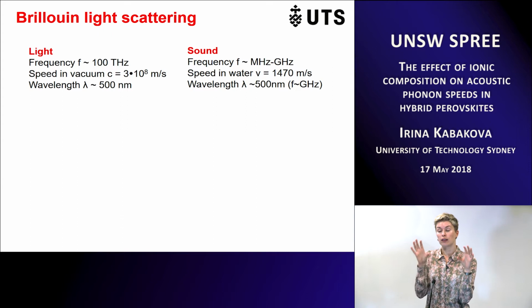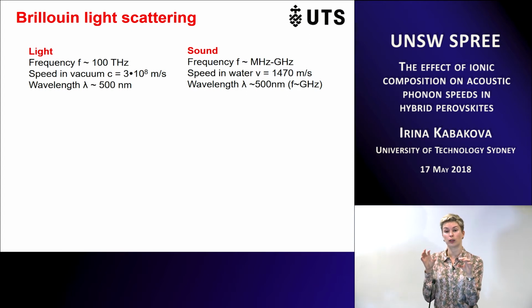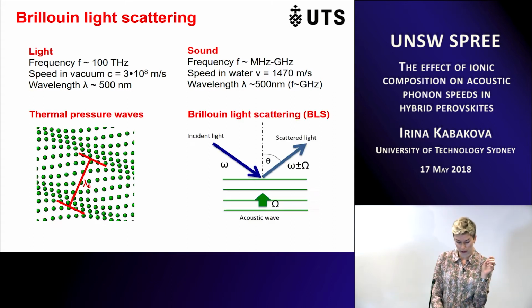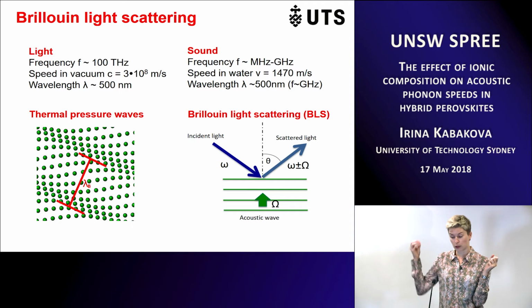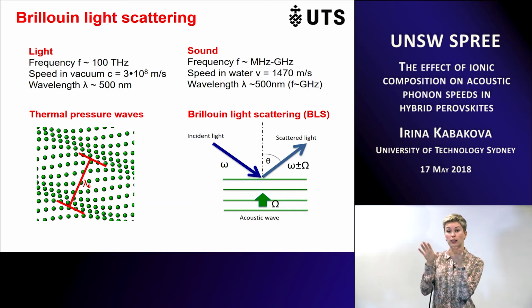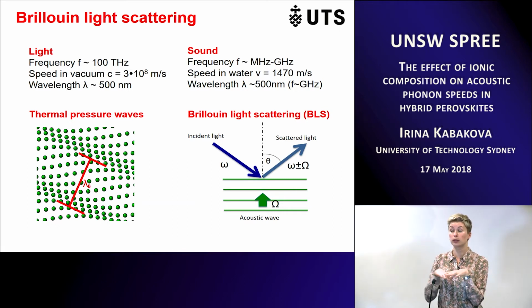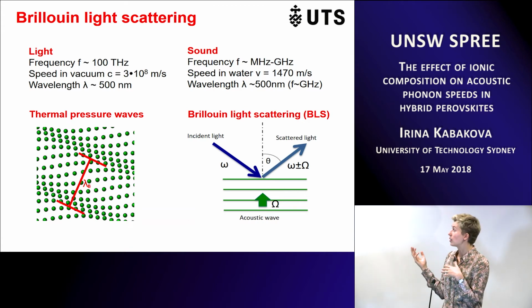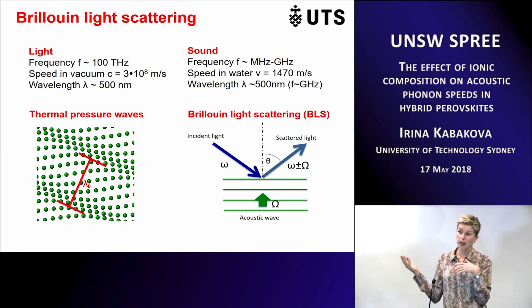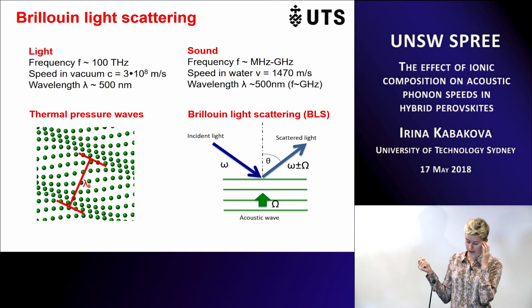This happens in the regime where sound waves are high frequency waves, so there are hypersound waves, gigahertz waves. It happens that both things actually have roughly the same spatial dimension, so they can interact and they can phase match. And that's what happens in the process of Brillouin light scattering. So the light, the photon, interacts with pressure waves that are intrinsic pressure waves due to thermal pressure fluctuations in the material, and the scattering happens. This process is phase matched and energy matched, so it goes with energy conservation.